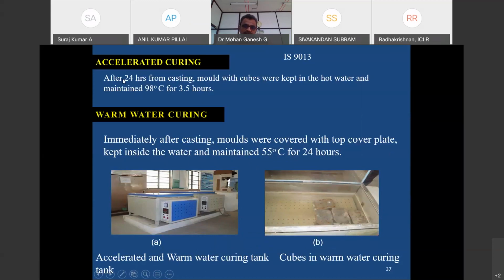For curing, we followed different types of curing, accelerated curing. What is the meaning of accelerated curing? After 24 hours of casting, the mold with cubes was kept in hot water and we maintained around 98 degrees centigrade for 3.5 hours. After that, we demolded and tested, which gives nearly equal to the 28 day compressive strength of the concrete.